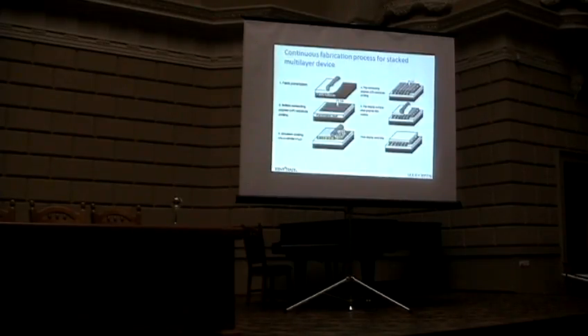So here is one of the issues. The other one is we saw this multi-layer stacking. That multi-layer stacking can be used to generate full color, but it requires a 3-layer stack. So if you want to stack 3 layers, in general you will have 6 substrates, right? To eliminate those substrates, one way is to use this continuous coating. This coating process you can use in lamination. So in this case, the substrate can be anything. What you need is just a planarization layer, and then you coat it on these conductive electrodes, and you put on this cholesteric material. Once they phase separate, you can continue to put on another layer of electrodes, and then put on this separation layer or protection layer. So if you repeat this process 3 times, then you can have 3 different layers of color material.